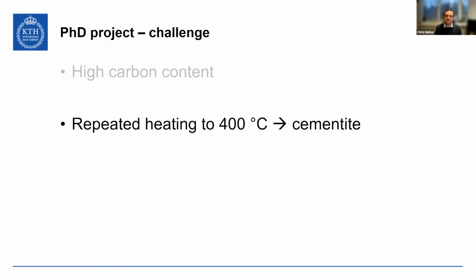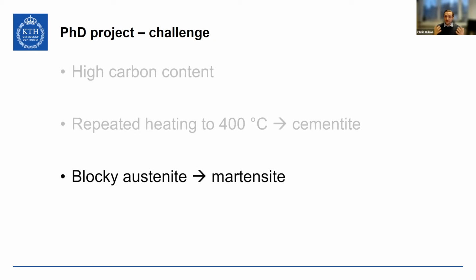That then means that the remaining austenite, the retained austenite, especially in the blocks, is very unstable, and when you cool it back down again to room temperature, you get a very rapid transformation or a very extensive transformation to martensite, which makes everything brittle and weak. And that was something which had been established by Thomas Sommer, amongst others, before I started my project.